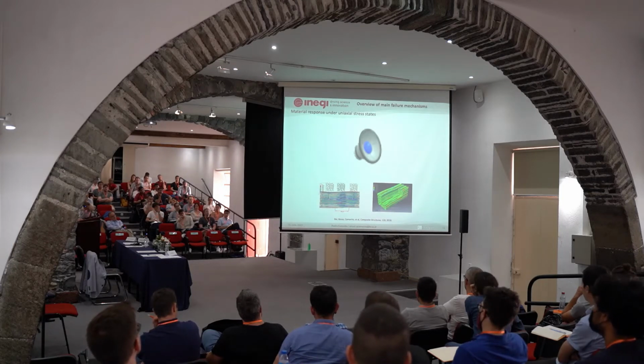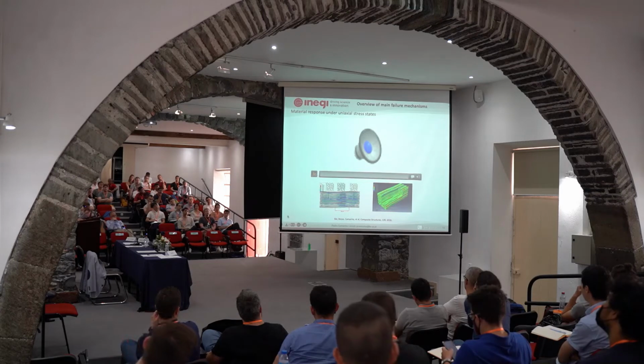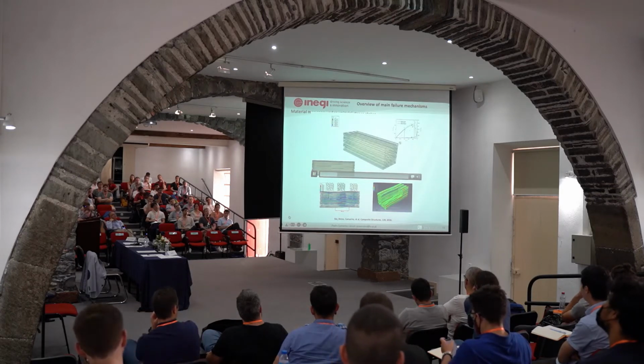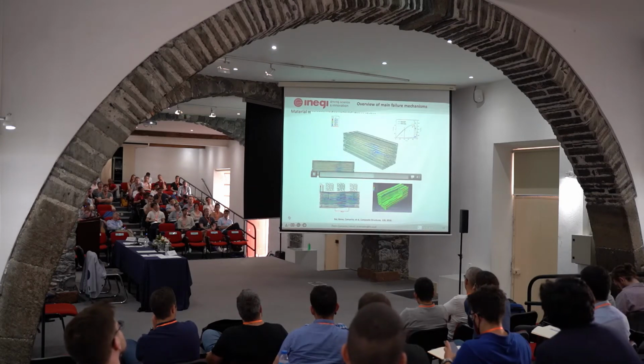So when we develop, say, failure criteria or damage models, we really need to take this into account. What Miguel Bessa and myself did, together with Camille from Northwestern University, was to run computational micromechanics. In this case, we have an initial imperfection, so we have some weakness so that we can localize damage. We are applying longitudinal compression, so this was a very heavy model to run. You can see here the shear stress, here shear strain. You can see the plastic strain, a region where we have the additional waviness, where plastic deformation occurs, and then you get this instability and the kink band created there.